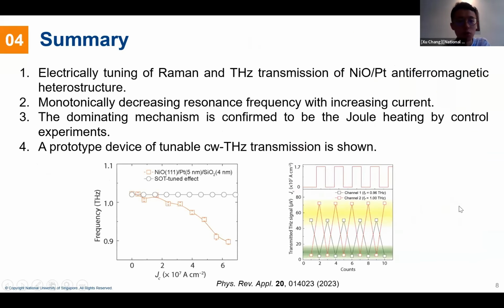Then I will give a summary of our recent work. We have shown the electrical tuning of Raman and terahertz transmission in nickel oxide platinum antiferromagnetic heterostructure. We have also shown a monotonically decreasing resonance frequency with increasing current. The dominating mechanism is confirmed to be Joule heating based on our theoretical calculation and control experiment. And at last, we have shown a prototype device of tunable continuous terahertz transmission. So that's it. Thank you.